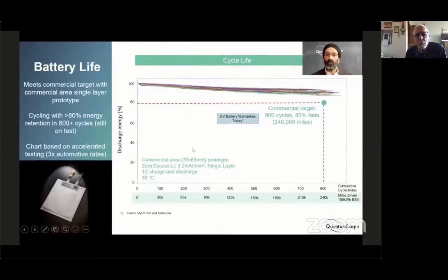They are not compromised test conditions. And you see the battery lasts over 800 cycles with well over 80% of capacity retained. The spec for commercial deployment of these batteries is in fact 80%, 800 cycles. So this is a really big milestone.